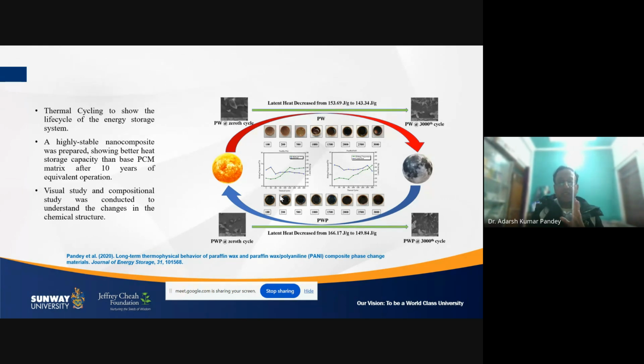The same way, for the nano PCMs, you need to find out what is the cycle. One charge and one discharge is equal to one cycle. So we have done experimental evaluation of our nano PCM, and we did 3000 cycles of this nano PCM. And after 3000 cycles, latent heat capacity we were especially focusing on. Initially at 0 cycle, it was 166 joule per gram, and it was roughly around 150 joule per gram even after 3000 cycles.